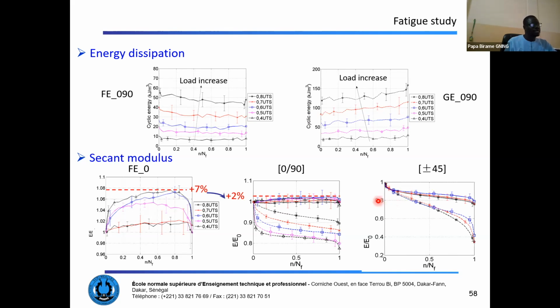On the contrary, when we compare it to glass here, we can see that the more they are loaded, the more we see a decrease of the secant modulus. At plus minus 45 degrees, for both types of specimens, the secant modulus diminishes. So this is an interesting result.